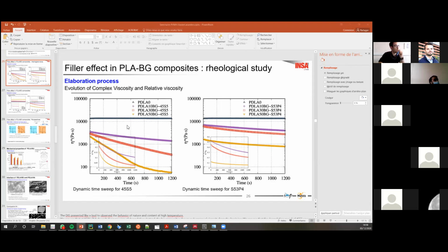Imagine increasing the shear rate, and after comparing for each time the viscosity and the modulus, we could see a decrease of this modulus as a function of the shear rate. Might not be only the shear rate, but also the strain amplitude. But okay, shear rate is part of the problem. So you expect that if you increase the strain amplitude or strain rate, you help to degrade the polymer a little bit.